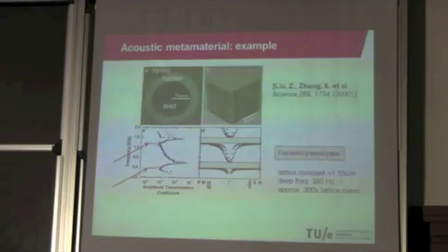This material was presented around the year 2000 by Liu, made out of lead spheres covered in a rubber coating and embedded in an epoxy matrix. They measured the existence of frequency band gaps. The interesting thing was that at least the lowest band gap corresponded to a frequency which can be recalculated back to a wavelength of approximately 300 times the lattice spacing. So this makes these materials particularly interesting for attenuation of low frequency, long wavelength waves. Another interesting point is that since their principle is based on a local resonance, they do not necessarily have to be perfectly periodic. Even if the periodicity is lost, their effect is still there.